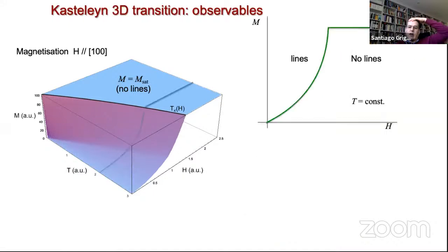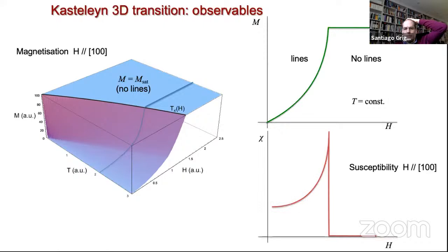So each time I put one of these, the magnetization decreases. So if I look, let's say, at constant temperature, what I expect to see of the magnetization as a function of field is something like this. So above the transition, it's perfectly saturated. Below the transition, there are these lines or these strings that lower the magnetization. So if I now look at the susceptibility, this would be one of the most distinguishing features of this type of transition, in the sense that I get something that looks like a divergence of the susceptibility on the low field side. This is where the strings exist. But because there are absolutely no excitations on the high field side, there's nothing here.